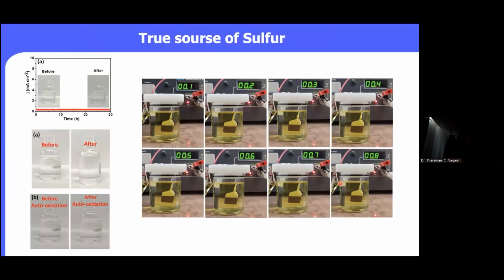Now, since our material is molybdenum sulfide, the question comes whether the sulfide oxidation is due to the presence of the sulfur in the material or due to the H2S. To confirm this, we have done some control experiments. That means we have performed chronoamperometric analysis for 30 hours at a particular potential where the sulfur oxidation occurs, without the presence of H2S.